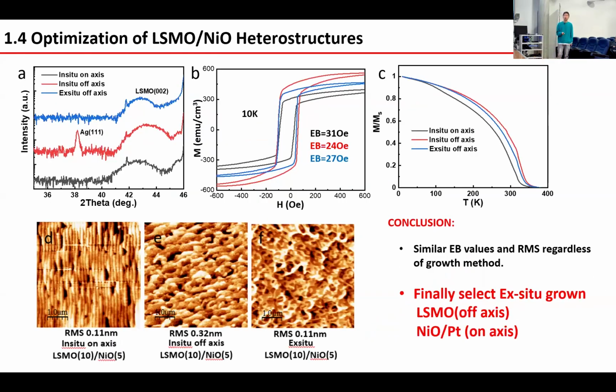And then I grow the LSMO nickel oxide heterostructures. As a growth method, we chose three ways: for example, the in situ on-axis, the in situ off-axis, and the ex situ off-axis. The in situ is to grow the LSMO, nickel oxide and platinum without taking out from the sputtering chamber. And the ex situ growth is to grow LSMO first, and then take it out from the chamber to pre-check the structure and the magnetic property, and then grow the nickel oxide and platinum again in the sputtering chamber.